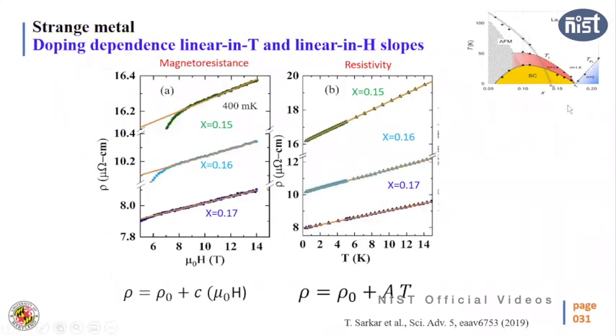So now if we go back to this phase diagram of this material, this LCCO, we saw this is the antiferromagnetism, there is a superconducting dome. Now for doping, starting from 15% to end of the dome, 17.5. So 15, 16 and 17, these 3 dopings, if we apply high magnetic field and kill the superconductivity, restore the resistive path, we can get the resistivity as a function of temperature. What we found, we have measured down to 20 millikelvin, and we can fit this resistivity as a function of temperature data using this equation, like a linear equation. Then one can calculate the value of A. So these are the fitting. We can calculate the value of A.